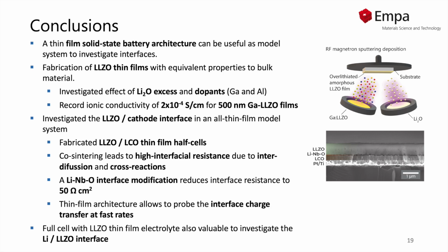We have shown that upon co-sintering, high interfacial resistance occurs due to interdiffusion and cross reactions, and a lithium niobate interface modification can significantly reduce the interface resistance to only 50 ohm per square centimeter. This allows fast interface charge transfer at fast rates. We finally showed that this architecture can also be useful to investigate the lithium metal LLZO interface.